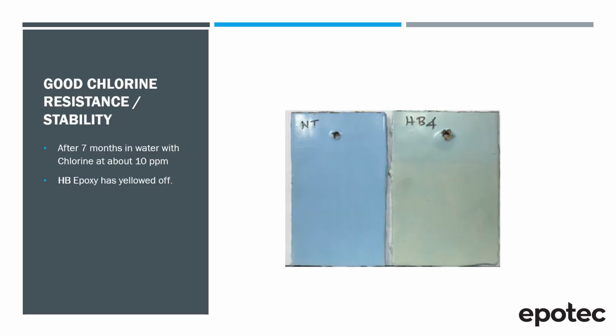We test the epoxy also for chlorine stability. Generally in pools you will find that the chlorine levels tend to go between 0 and 5 ppm, parts per million. It's rare for chlorine levels to be held at any length of time much more than that. This test was run over 7 months in water. The chlorine has little to no effect on the NT. You can see the old HB on the right-hand side has a distinctive line where it was immersed and it has some bleaching on it.